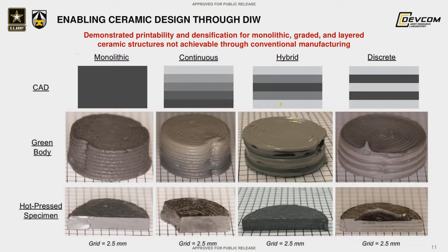So you can see there's a pretty drastic change in volume as you get rid of the almost 50 volume percentage of pores in the green bodies and take them to fully dense ceramic parts.